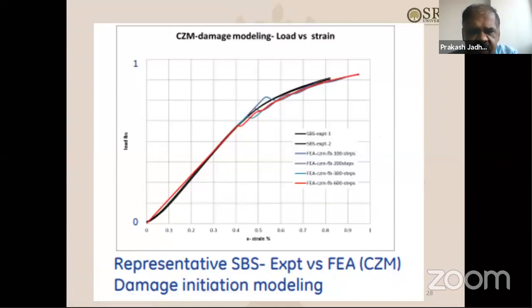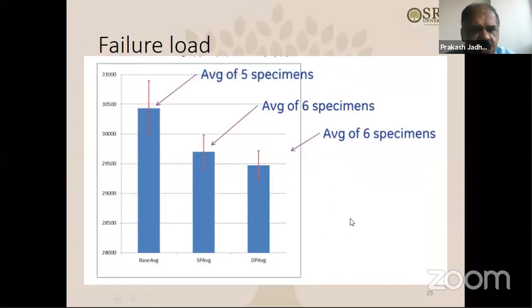Okay, so next. As far as the failure load is concerned under this short beam shear testing, you can see the average of 5 or 6 specimens. There are specimens without any ply drop inside, a constant thickness specimen. There is a specimen with a single ply drop located at the highest possible interlaminar shear stress point. And there is also a double ply drop, 2 plies dropping at the location where maximum interlaminar shear stress is occurring. So you can see the difference in the failure loads.